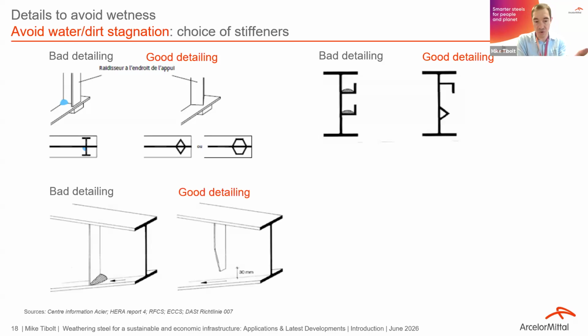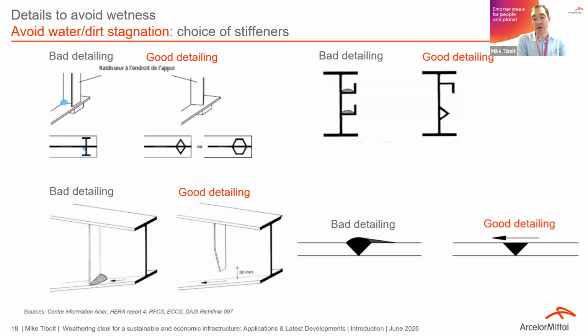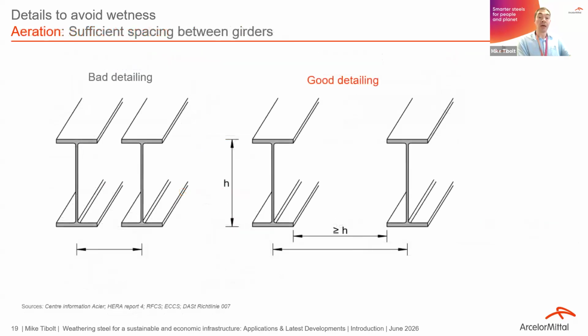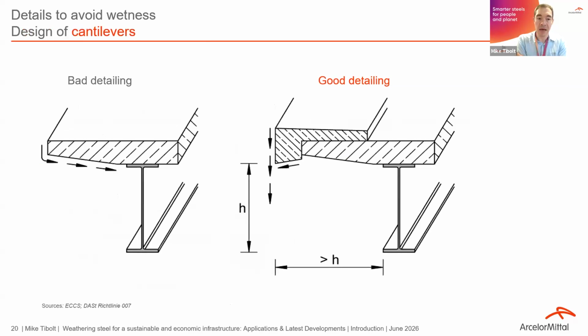The same holds true that you should always leave it open on the bottom flange and incline the bottom flange so that the water and the dirt can drip off. And for the welds, anyway, this would be the case for bridges, you should grind them flush so that, of course, you have no local humidity at the weld root. And also the distance between the beams should be at least as high as the height of the beam, so as to have a good aeration and a wet and dry cycle in the beams. And of course you should avoid that the water can drip along the beams and drip then on the bottom, because then it can accumulate some rust particles, leading to stains.